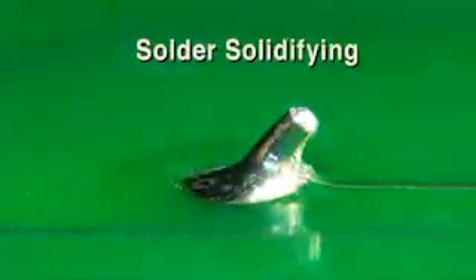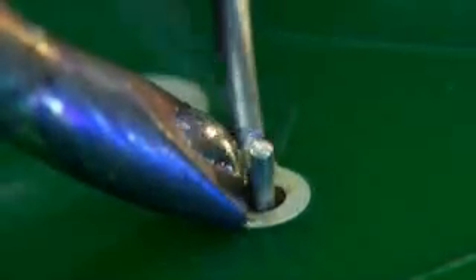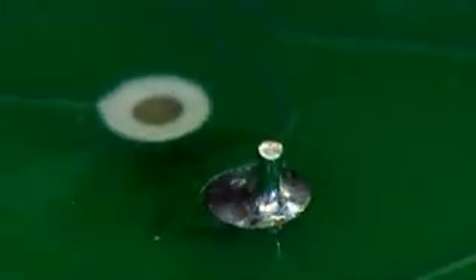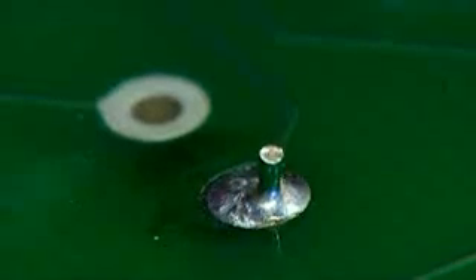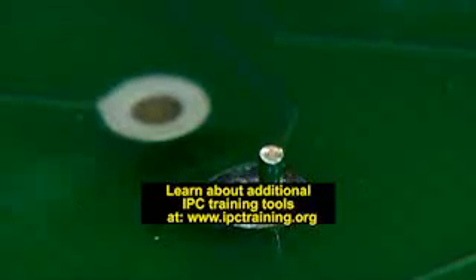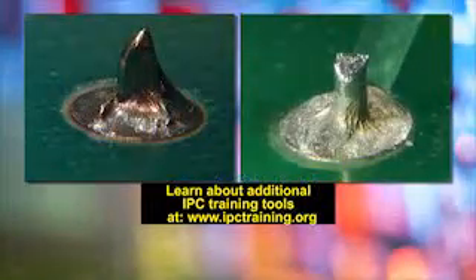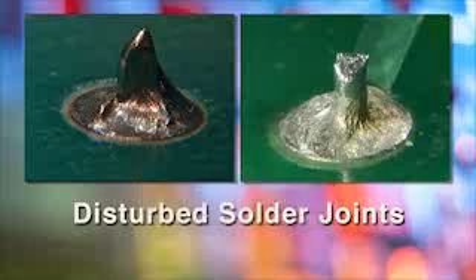The amount of time solder takes to solidify can also affect the strength of the solder joint. While the solder joint is cooling and the solder is not yet solidified, any bump or vibration can break, loosen, or otherwise damage the electrical and physical properties of the solder connection. Again, the result is called a disturbed solder joint. If the solder appears wrinkled or distressed, this indicates a mechanical weakness, which can eventually cause electrical failure.